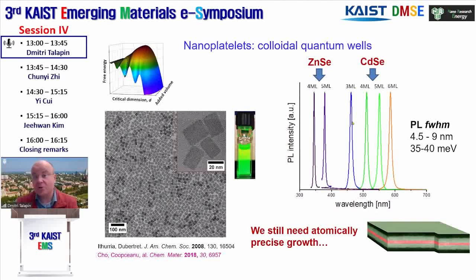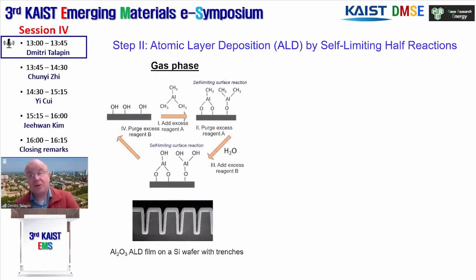And these are all ensemble spectra. So these materials show incredibly narrow emission. But that's what we can achieve by controlling nucleation. But if we want to turn it into a methodology for making arbitrary complex structures, we need to couple it to atomically precise growth. So in order to achieve atomically precise growth, we can take inspiration from the method of atomic layer deposition, or ALD, which is used at every semiconductor fab for growing conformal coatings on silicon wafers in the CMOS process.